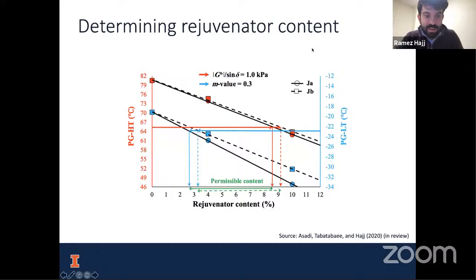This work is co-authored with one of my PhD students and his master's advisor. We noticed that in this case, there's a pretty wide range that you can use. For example, here are two types of rejuvenators. JA is an industry rejuvenator, and JB is a waste cooking oil rejuvenator. In both of these cases, you can use almost anywhere from 3% to 8.5%, 9%, and you can still maintain the same grade of your binder based on the PG system, which is the classification system we use in the US.